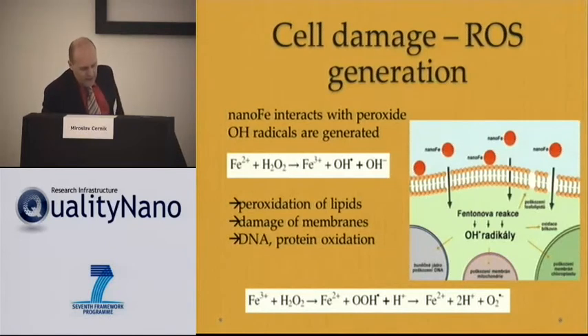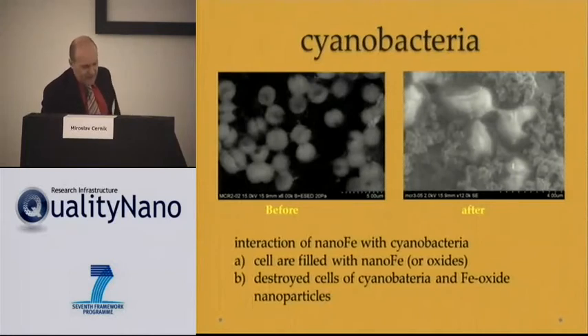This is due to interaction of the iron with peroxide, and it produces OH radicals, which are danger for, of course, for the cell. We did some study where we applied the iron for cyanobacteria, where of course the negative effect is sort of good because we want to destroy the cyanobacteria, and it shows picture left is just after the application, where the nano iron is sort of captured by the bacteria, and this picture is after some time where the cells are totally destroyed, and you see the residue of the cells and the iron oxide outside, so that we are able to kill this cyanobacteria, which is good for